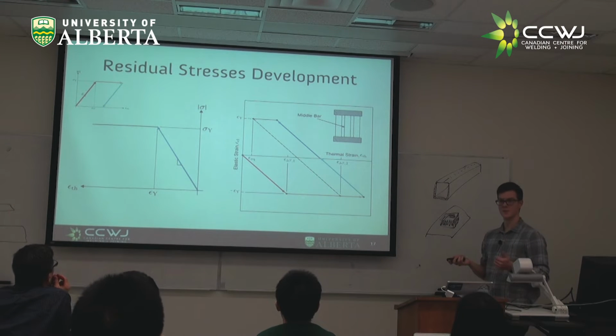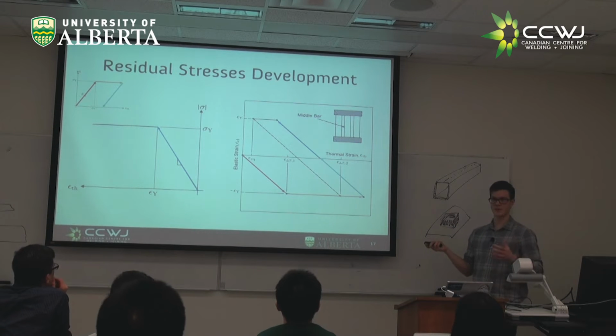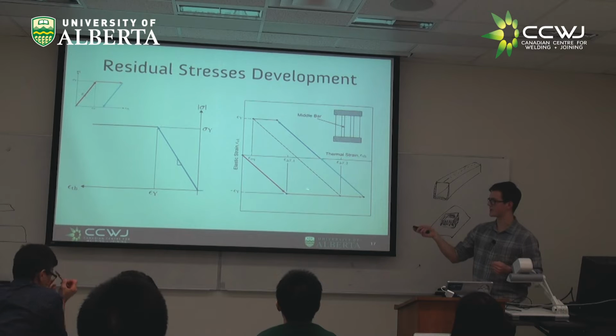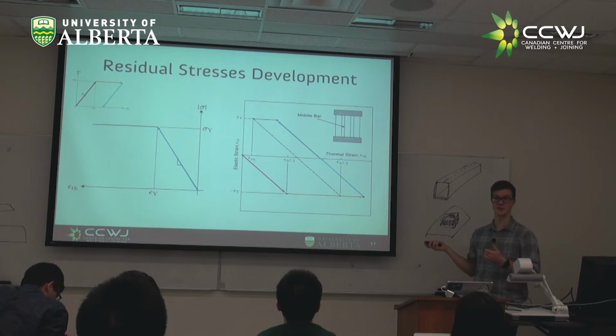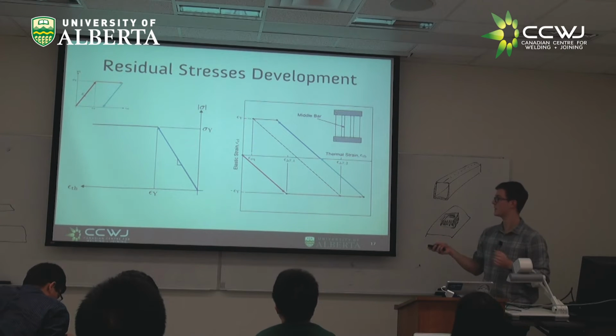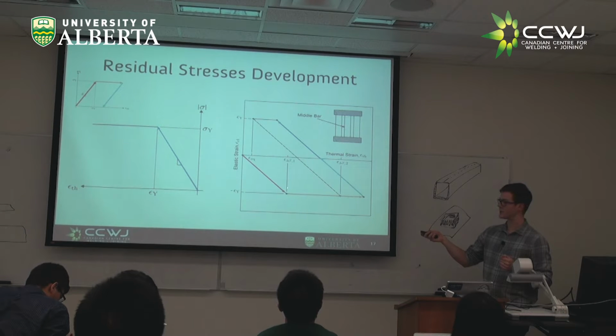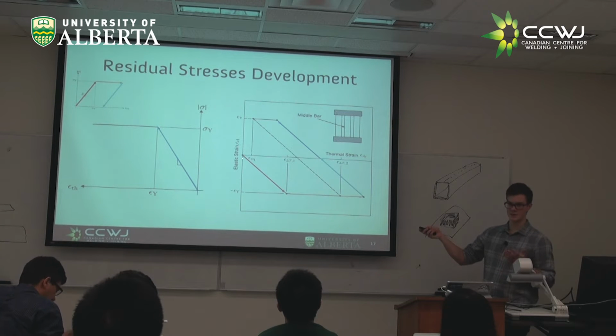Does everyone see that? That's why we end up with tension in our weld, and it's not because of just thermal strain, it's because we had all of this extra strain that we couldn't accommodate, which became plastic strain. So you can imagine if you're at this point when you weld, this is kind of your critical point. Any temperature beyond this point, any thermal strain beyond this point, becomes plastic strain. And all of the plastic strain beyond this point eventually is going to lend itself to stress. If we're here, when we return back along this path, we have zero stress.